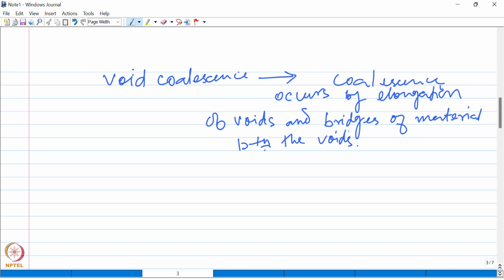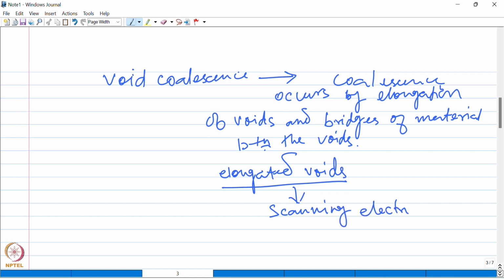So if you look at the fracture surface, you would actually find these elongated voids. But this can be seen properly under an electron microscope like a scanning electron microscope. Because the fracture surface is quite rough, in order to see it as it is, you cannot really use an optical microscope, which needs a polishing of the surface and all that. So if you take the fracture surface and observe it under a scanning electron microscope, you would see these voids. Let me show you how it looks when you observe it under the SEM.